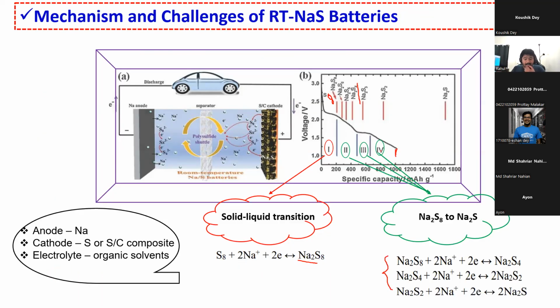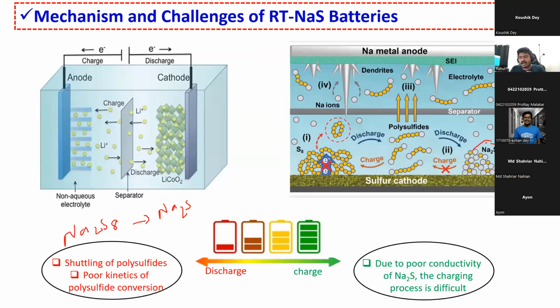Okay, now I have talked about the major issues and problems in sodium sulfur batteries. Now what is our lab doing? I told you there is a shuttling effect problem, a poor kinetics problem, and when we are talking about charging, there is the problem of the poor conductivity of Na2S, so it's difficult to charge the battery. So in our lab, we are developing a kind of catalytically active anchoring material which can bind the polysulfide so that it won't go to the electrolyte. It will convert the polysulfide from Na2S8 to Na2S at a much faster rate. And during the charging process, it will break the sodium sulfur bond and allow the sodium to diffuse very fast when compared to the pristine sulfur cathode.